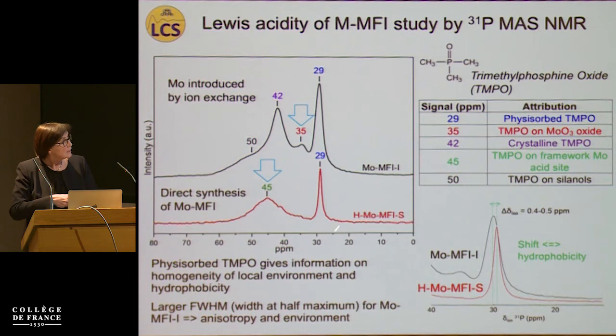And we have also seen that the peak which is attributed to the physisorbed TMPO is shifted considerably in comparison to a sample which was prepared via ion exchange. This shift is also a signature of a change in hydrophobicity, and we could also see that the ion exchange sample has another peak at 50 ppm, which corresponds to silanols, while the atomically dispersed molybdenum introduced directly in the MFI framework does not contain this peak.